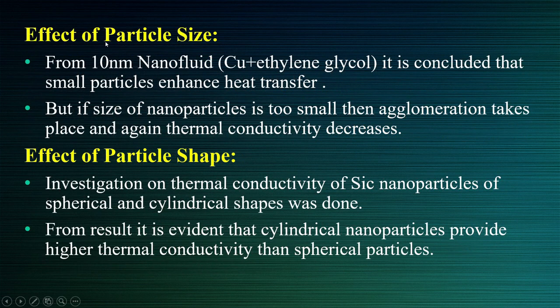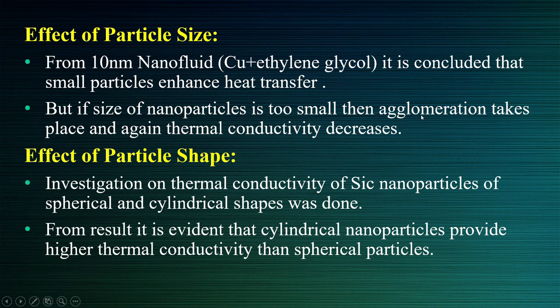Regarding the effect of particle size on thermal conductivity, for copper plus ethylene glycol nanofluid with 10 nanometer particles, it is concluded that smaller particles enhance heat transfer rate. However, if the nanoparticle size is too small, agglomeration takes place and thermal conductivity decreases again. Very small particles also increase pumping power and viscosity, ultimately lowering the heat transfer rate.